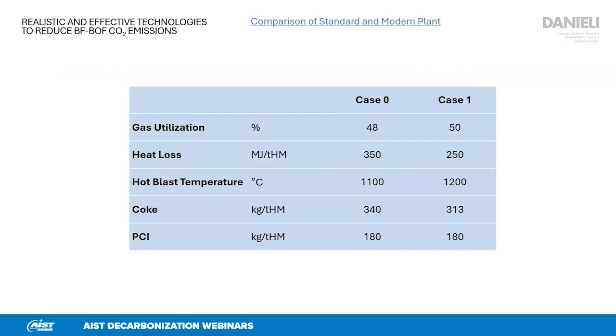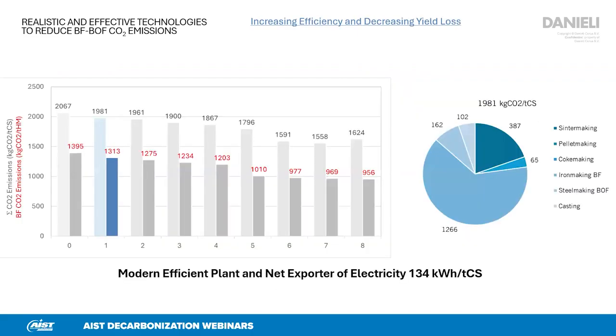This will reduce the coke rate whilst retaining the PCI rate. And by reducing the coke rate, overall carbon emissions will be reduced to a level of approximately 1,981 kilos of CO2 for 1 ton of crude steel. And this reference steelmaking plant, a modern reference steelmaking plant, is actually a net exporter of electricity of around 134 kilowatt hours for each ton of crude steel, by nature of combustion of any excess blast furnace gas and coke oven gas, and use that heat to generate export electricity.